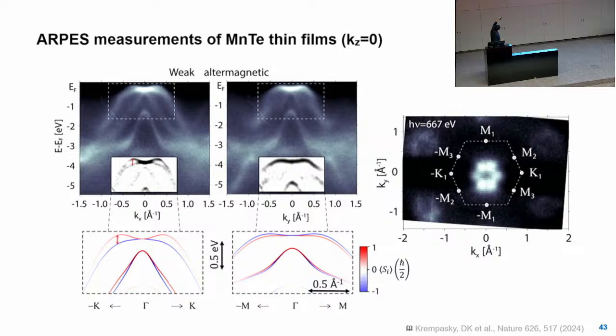So these data are a bit filtered compared to the raw data, and you actually can see that there are these bands, and this corresponds very nicely to these calculations which the theoreticians do. And these tell us that indeed we found that there is this splitting of these two types of spin polarizations of the electrons. So we have an upper branch, which is the red one, spin up for example, and we have the spin down branch, which is the bottom one.